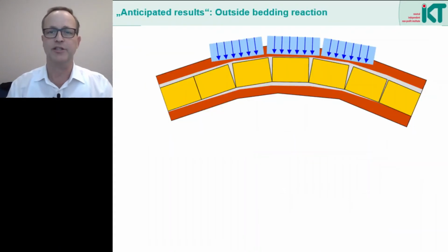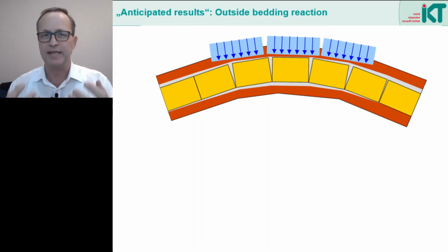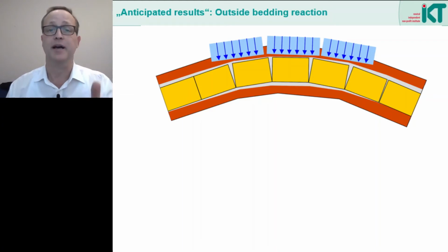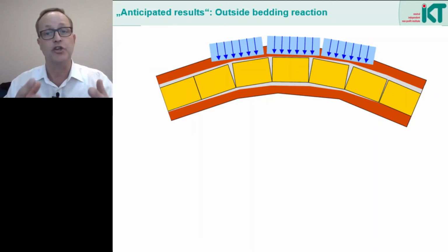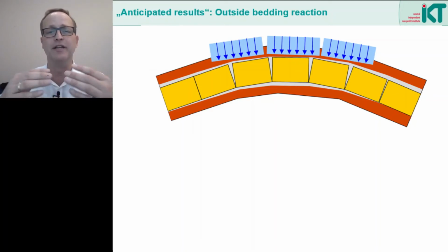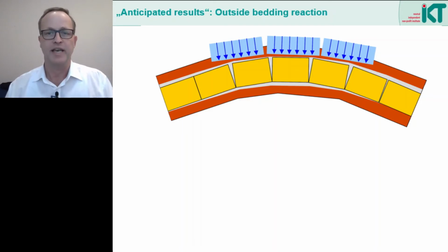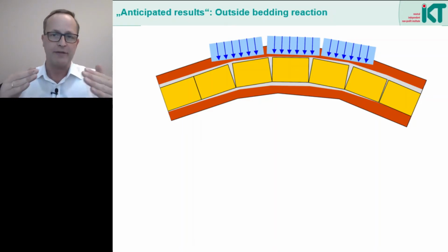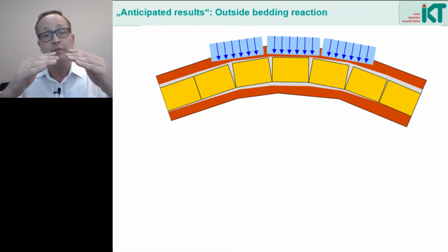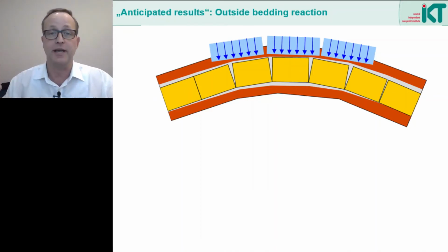Here we see a sketch that was usually imagined in the statics as a typical loading for a curve. Of course, before our results were known. The pipes are all evenly distributed in the curve, and as a bedding reaction it is assumed that the pipes experience an evenly distributed bedding pressure on the outside of the curve. This seems very logical at first glance, because if we press the string from the left and from the right, the resulting force must go outwards. And an even bedding, well, that seems a quite natural assumption.